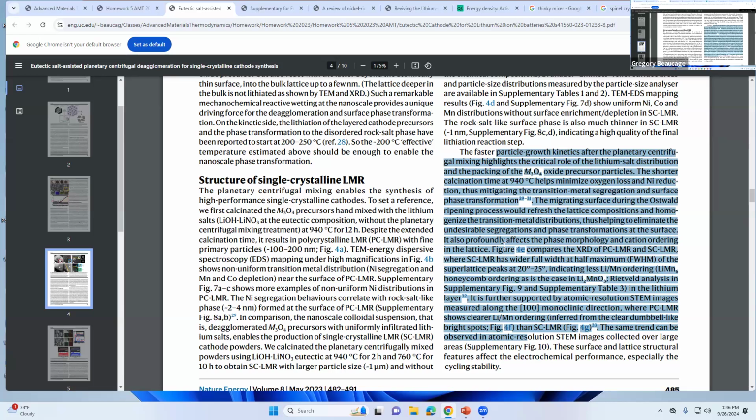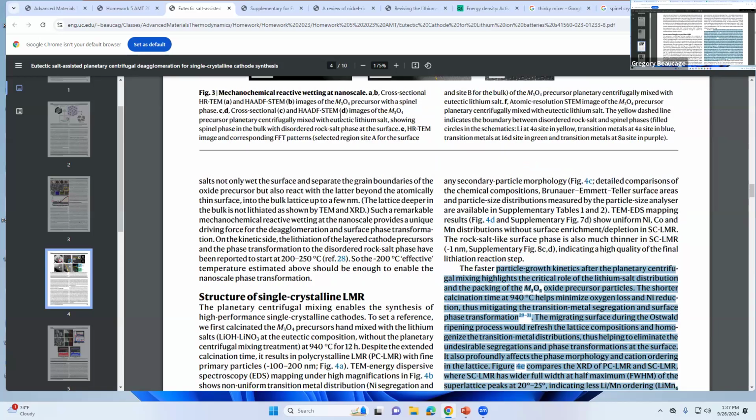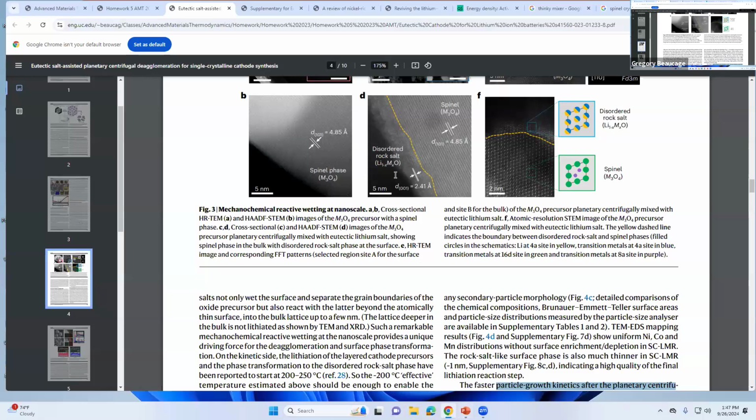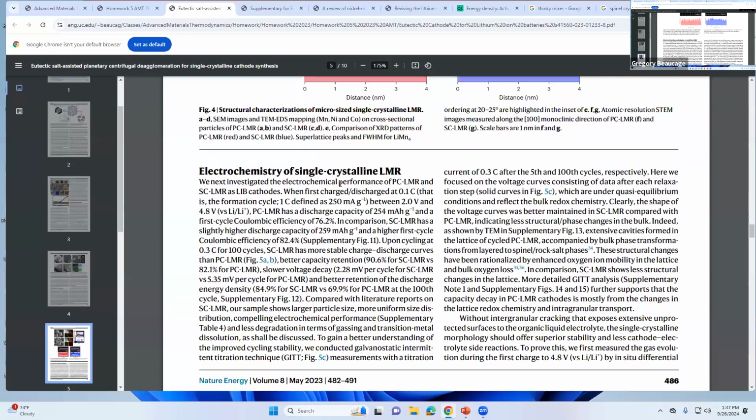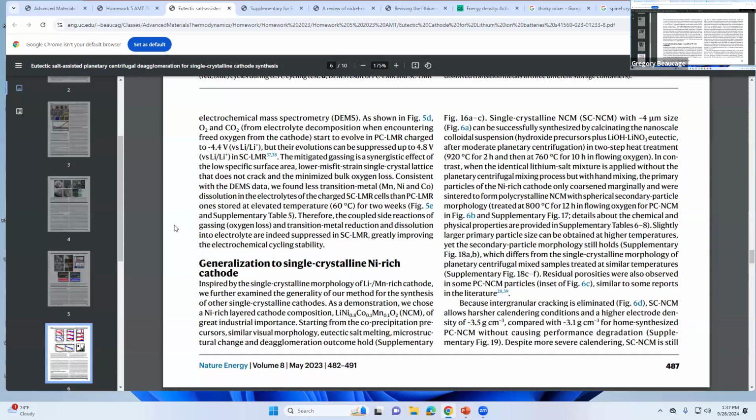So it's like depleting. You put so much lithium in your battery, you want to use it for power, but you can't because it's stuck in the rock salt. And then also it's a barrier for the lithium to get into the part that's going to release it and make the battery work. So it's a good thing to make that thinner. That might be more important than the business about making big crystals. He has a thinner surface layer. So anyway, that's about it. Hopefully you can learn something about batteries by fishing through this thing.